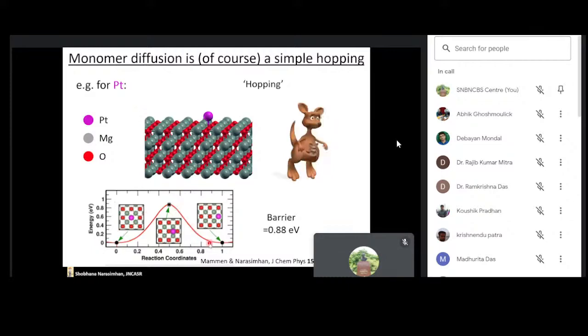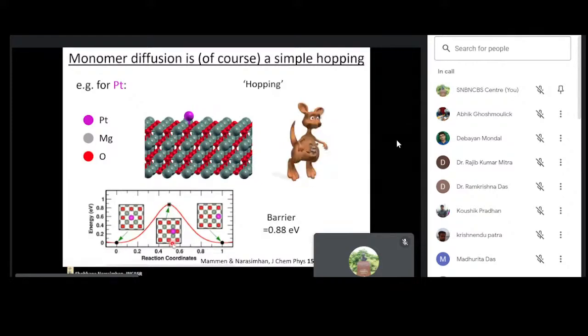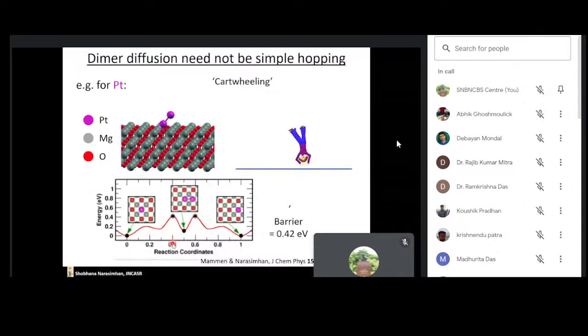So it has a minimum where it sits above an oxygen atom, and then it sits at a bridge site, that is the transition state, and then again a minimum. And we can calculate the barrier for this hopping process, and it's 0.88 electron volts. However, if you look at a dimer of platinum, then it does not move by this simple diffusion process.